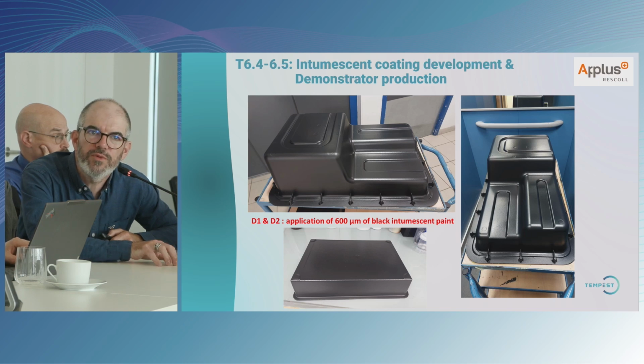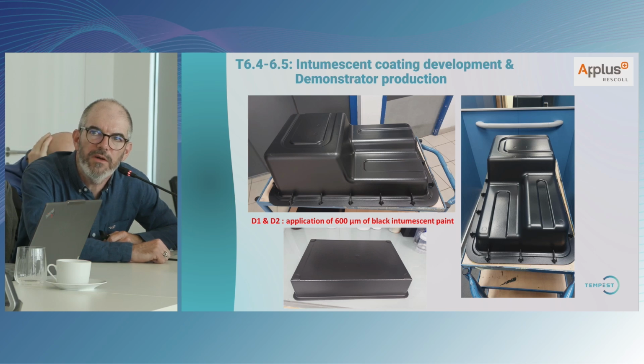So it was for the 3 cold spray coatings, functionalizing the housing internally and externally, and we also used, let's say, a more standard paint, which is solvent-borne, but for, again, fire protection, but for that case on the outside of the coating, of the housing. So we used a 2K epoxy intumescent paint that was deposited on the outside of the demonstrators, and you can see that the coating was quite nice and uniform, and we deposited a 600 micron black paint.